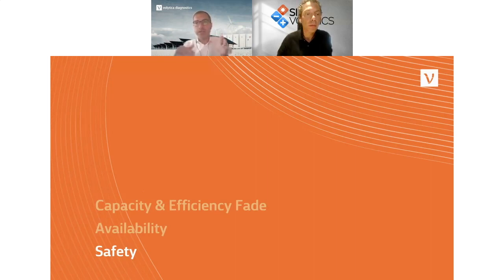Some cells on the outside will degrade slower than on the inside, where you cannot get rid of the heat, which will in the long run very, very likely lead to availability and sometimes even safety problems. But there are sophisticated air cooling systems that are also good. And I'm not judging what the manufacturers would come up with, innovative things.